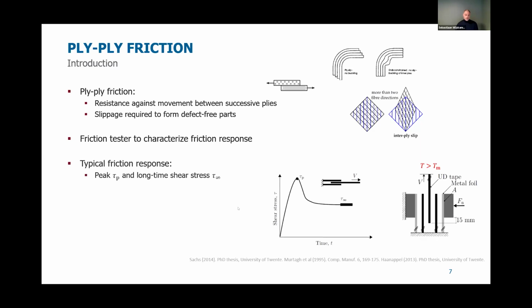Typical friction response is that the shear stress grows, reaches a peak, and then drops down to a certain plateau value. So we recognize a peak and a long-term shear stress. In the material models, we often use the long-term shear stress. It's easier to model. Or we pick the peak stress. So AniForm offers both options. Most of the time, the long-term shear stress is considered here.